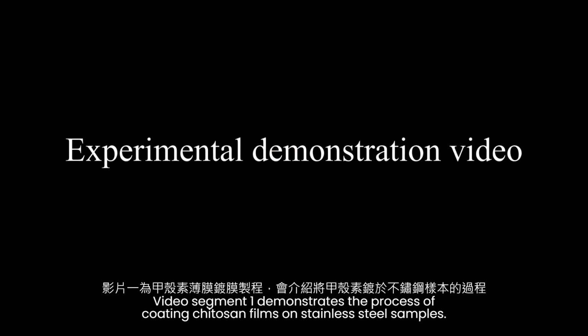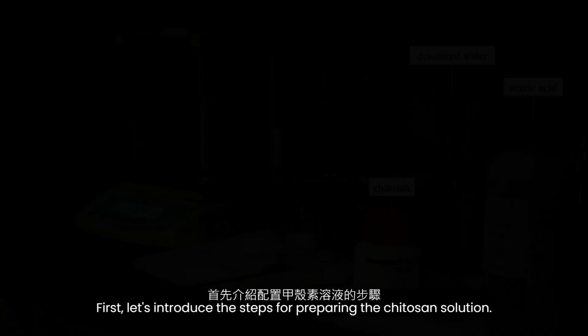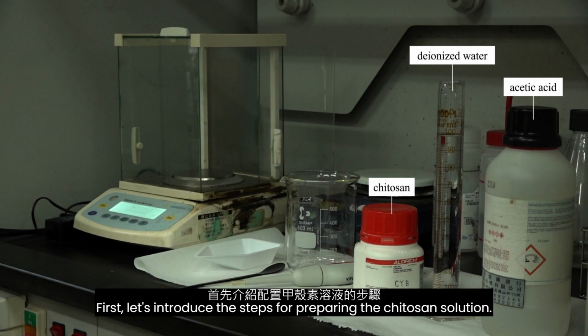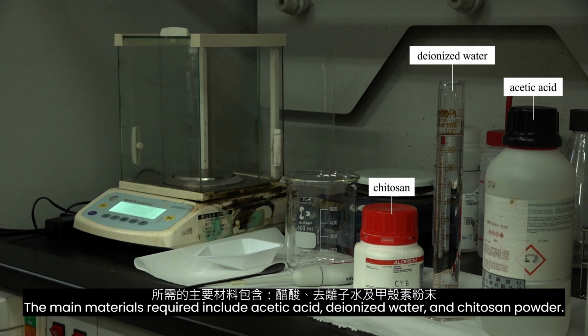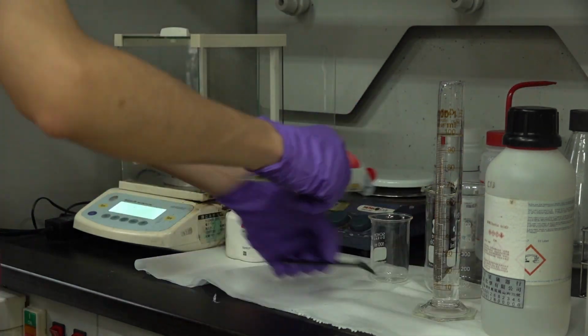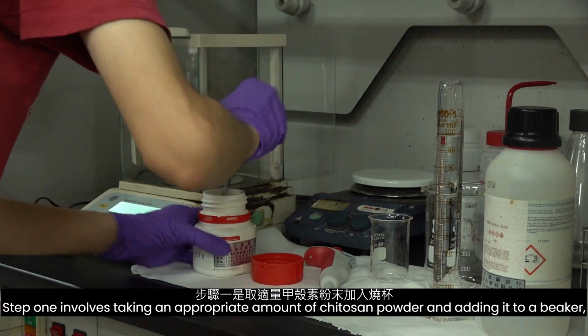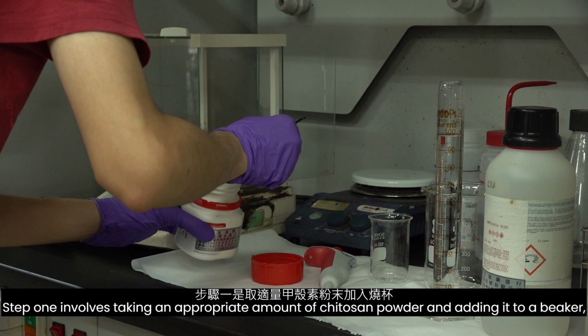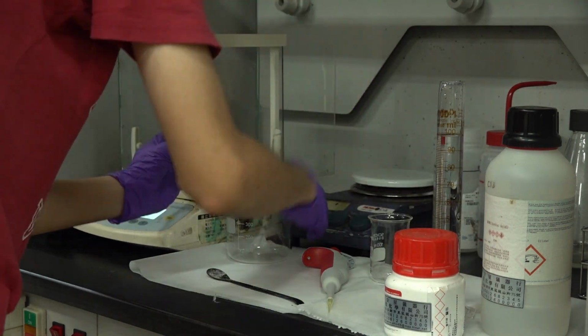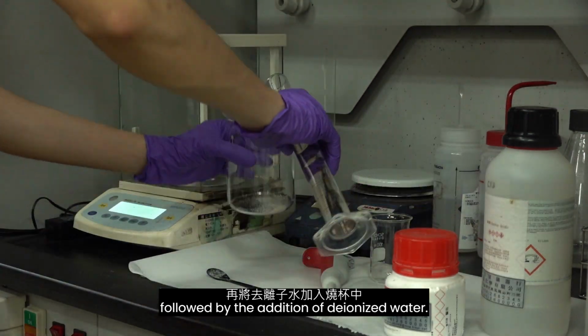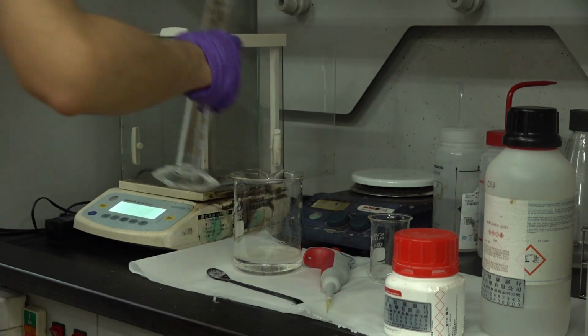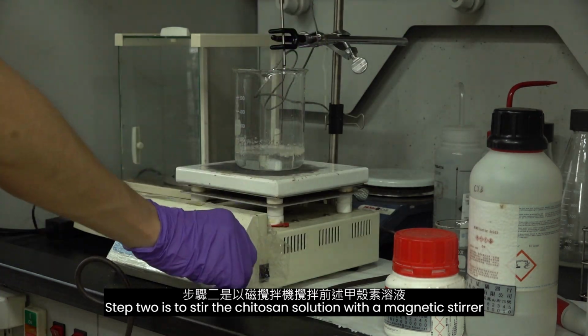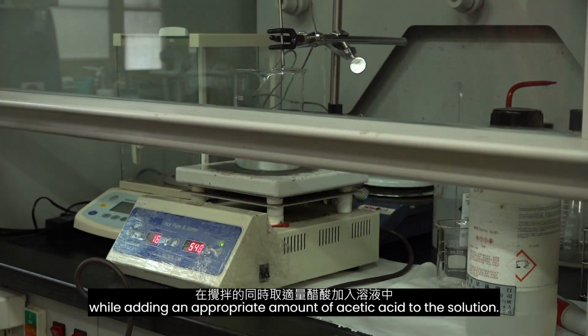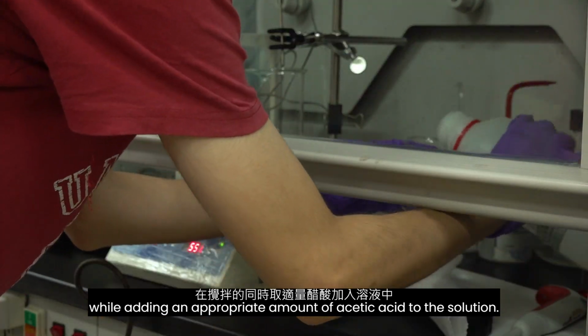Video segment 1 demonstrates the process of coating chitosan films on stainless steel samples. First, let's introduce the steps for preparing the chitosan solution. The main materials required include acetic acid, deionized water, and chitosan powder. Step 1 involves taking an appropriate amount of chitosan powder and adding it to a beaker, followed by the addition of deionized water. Step 2 is to stir the chitosan solution with a magnetic stirrer while adding an appropriate amount of acetic acid to the solution.